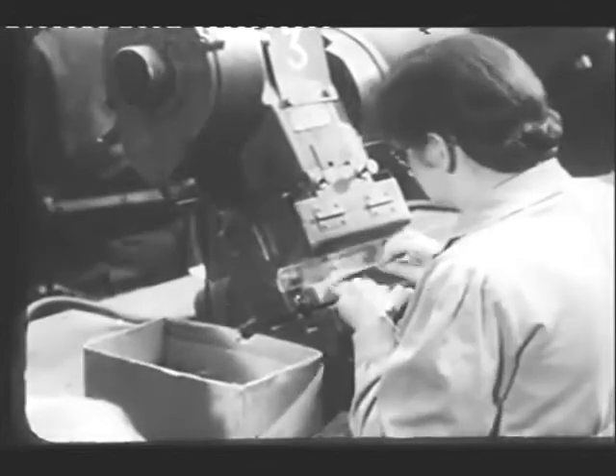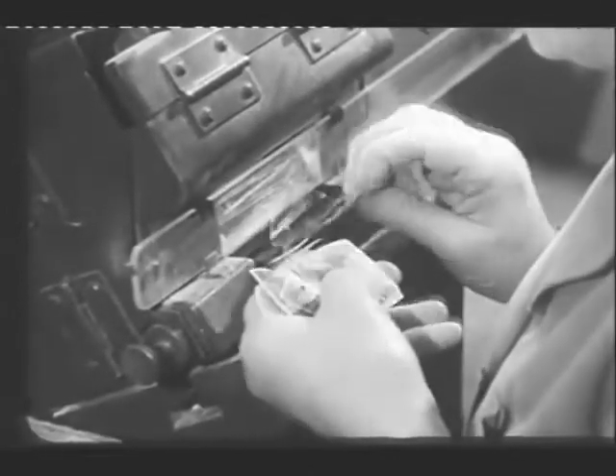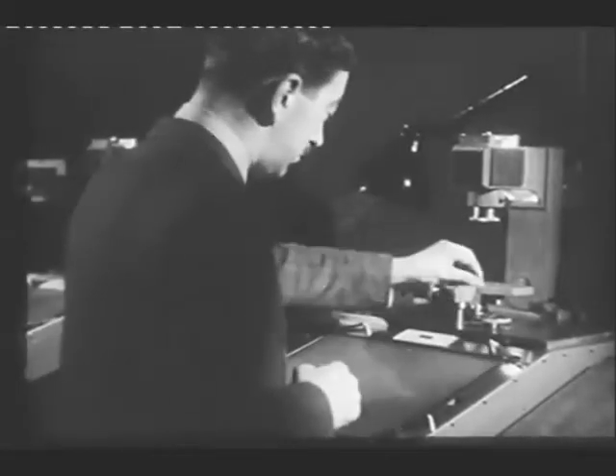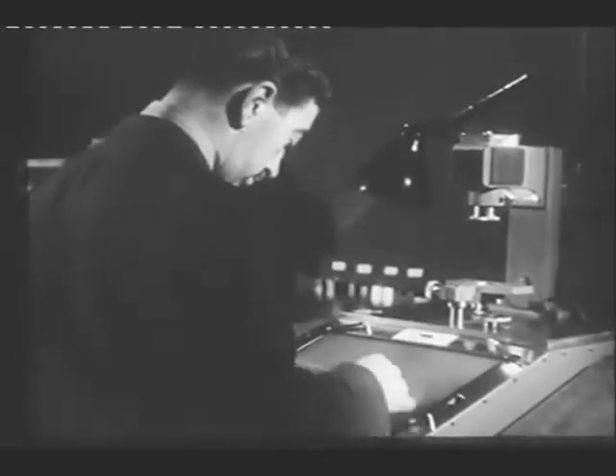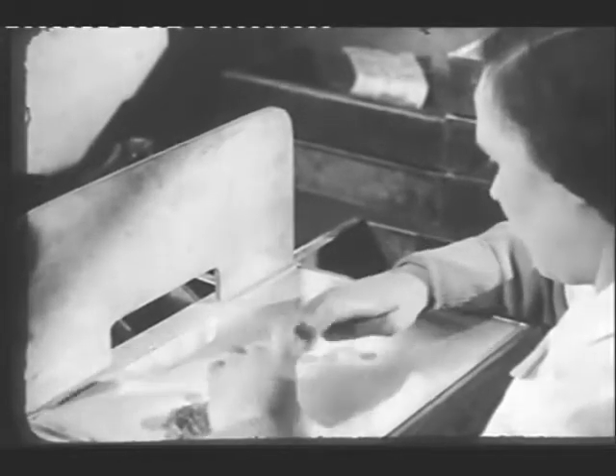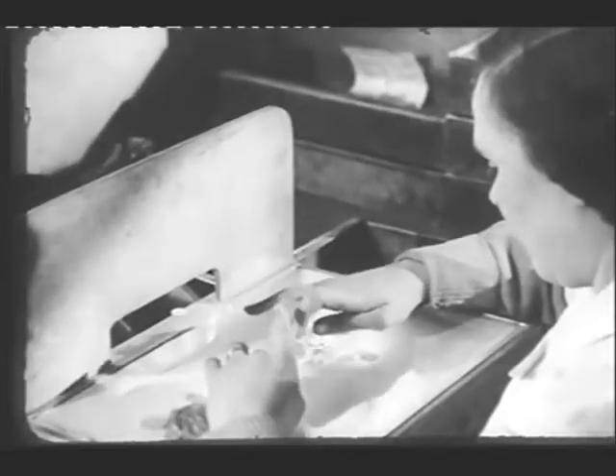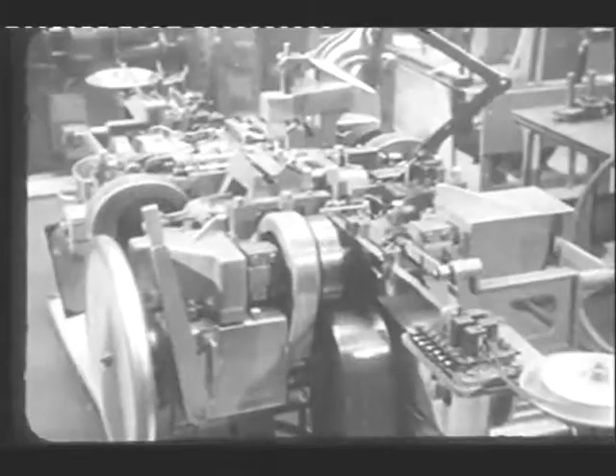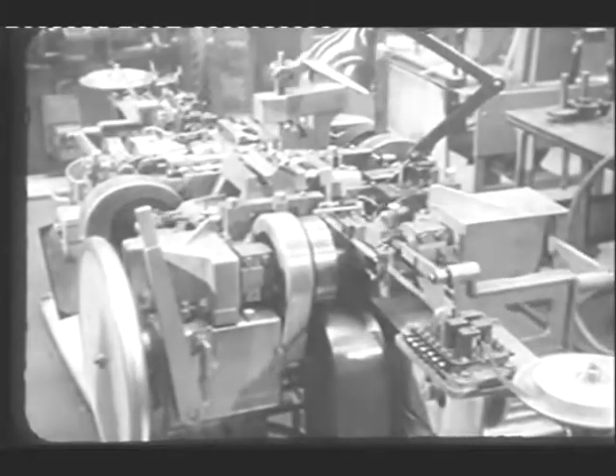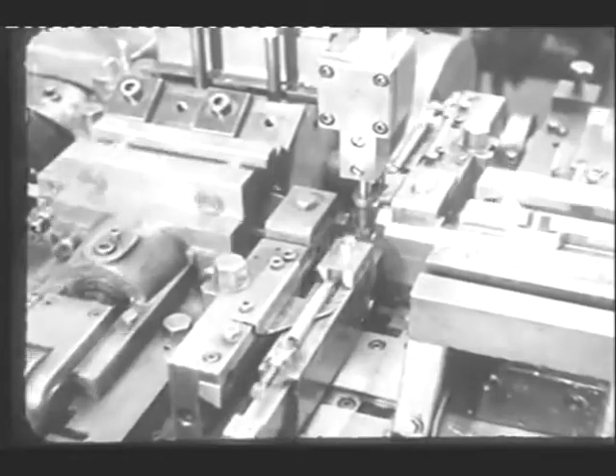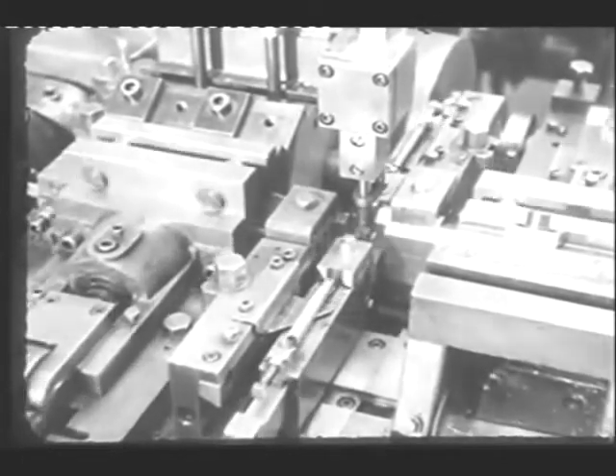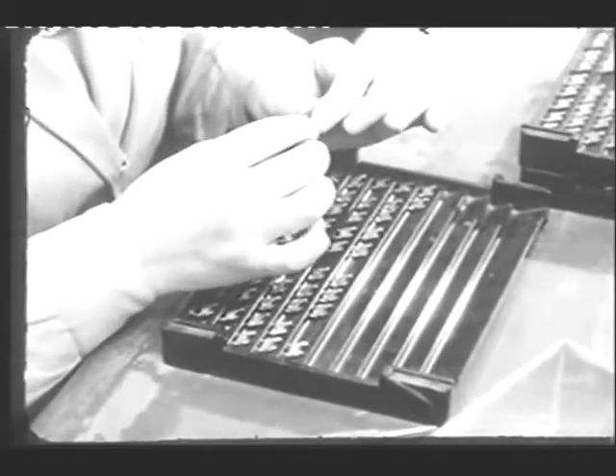Now for some other valve components. Mica discs are stamped out of sheet mica and are checked for size and position of holes by projecting their image 30 times full size onto an illuminated screen, where the dimensions can be measured to within 1/500th of an inch. After this, the discs are examined and any broken ones rejected. Anodes are stamped out of sheet metal, usually nickel. This machine produces complete anodes, accurately stamped, bent to shape and lock-seamed from flat nickel strip. Each single anode is carefully inspected.